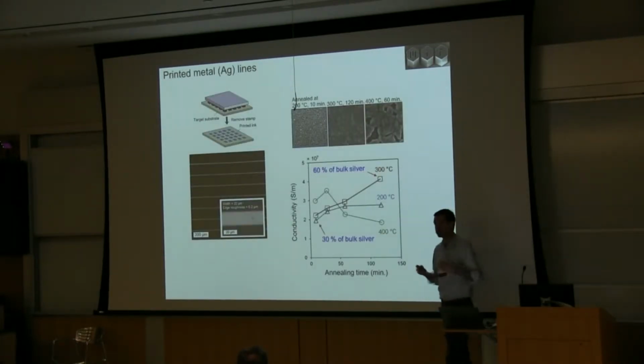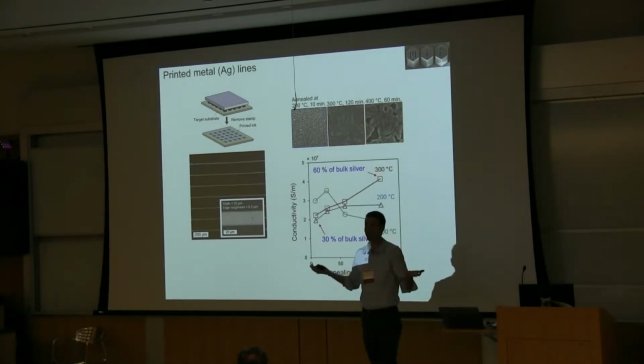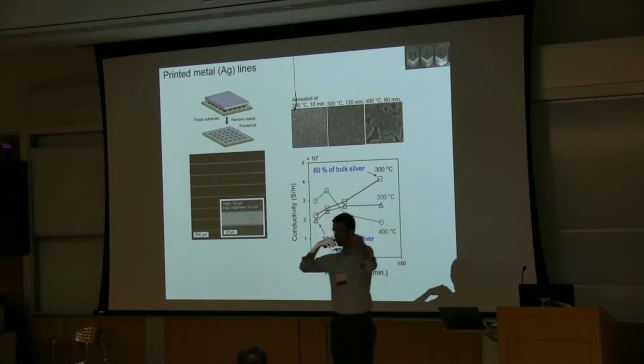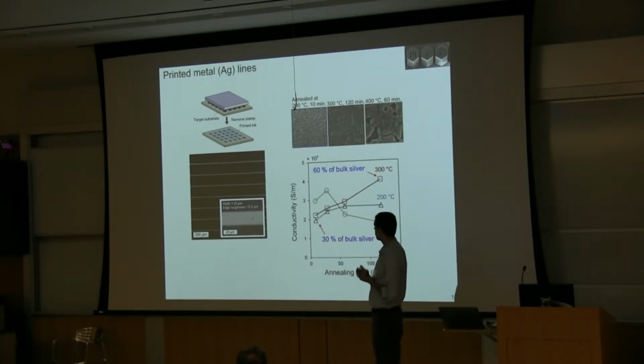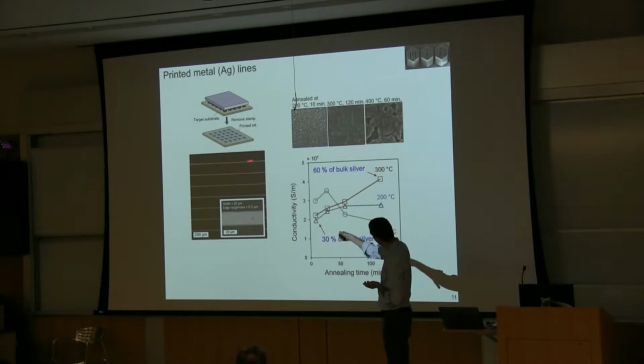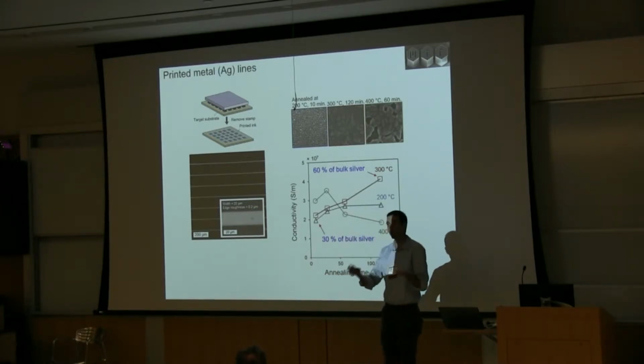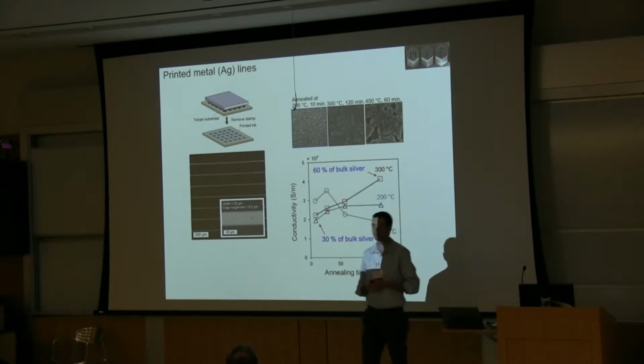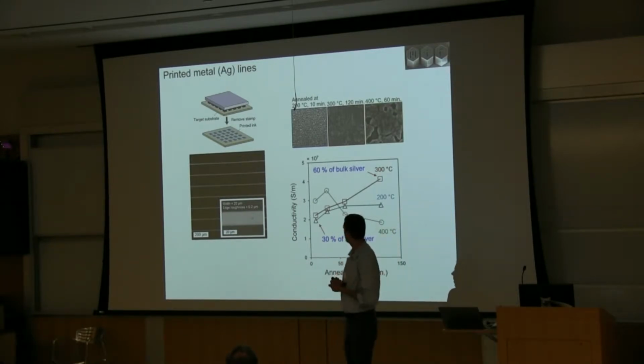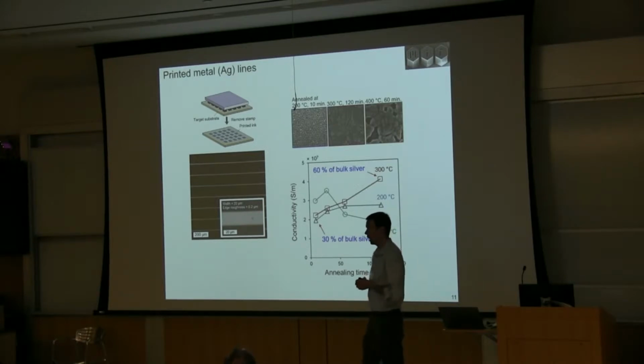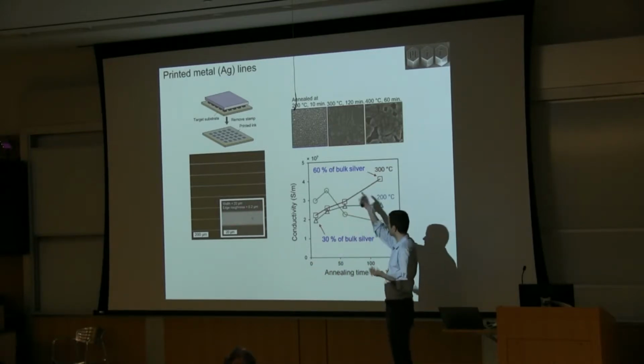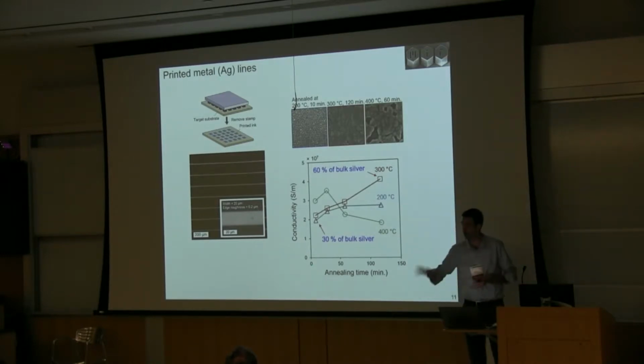The simplest kind of feature structure you can print is metal lines. So if you want to make any kind of circuit or interconnect, imagine connecting to the touch pixels on your display, you would print lines, and this is just taking a stamp of carbon nanotube forest with linear features, and these are the silver ink features that result. You let the ink be printed, you let it evaporate, and then you put the pattern in an oven because you have to anneal the nanoparticles into your final metal, and by optimizing the time and temperature, you can make conductive metal features that are, in this case, about 60% of the conductivity of bulk silver. So that's a basic test that this process works and produces high-quality conductive features.